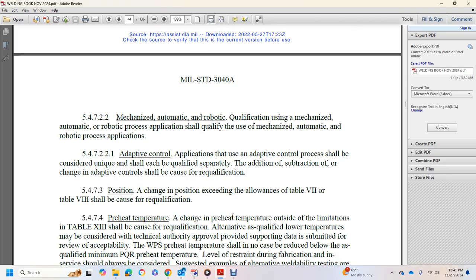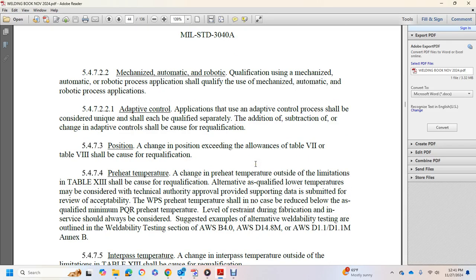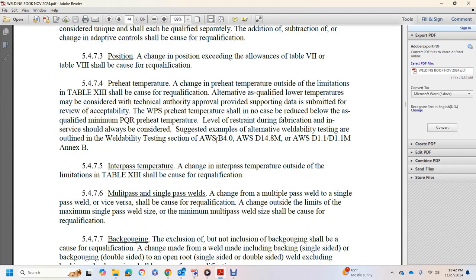See the columns in Table 7 and Table 8 for requalification. Preheat temperature: a change in preheat temperature also has limitations in Table 13 and should call for requalification. An alternative requiring a lower temperature may be considered by the technical authority, with supporting data submitted for review of acceptability against the welding procedure specification. The WPS preheat temperature shall in no case be reduced below the as-qualified minimum PQR preheat temperature. The level of restraint during fabrication of the service should be considered. For example, suggested alternative weldability testing is outlined in the welding testing and weldability testing sections of AWS B4.0, AWS D14.8M, or AWS D1.1/D1.1M Annex B. Interpass temperature: a change outside of the limitation in Table 13 calls for requalification.